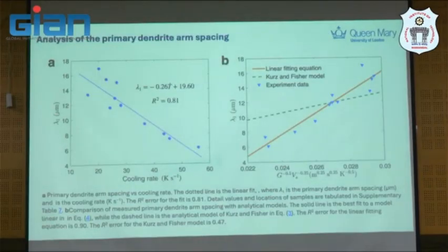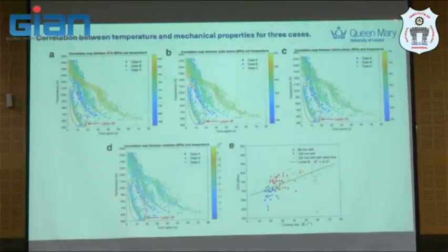So they characterize or analyze the primary arm spacing as a function of cooling rate, because if you are a metallurgist or material scientist, this is a very important aspect to understand. It will tell you a little bit more about the defects which form in the later stage. And there is some correlation across the many cases that they ran. Again, this is impossible without a neural network, if we want to relate the temperature field and mechanical property.